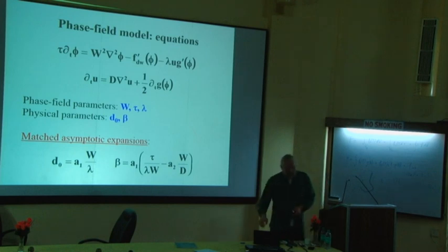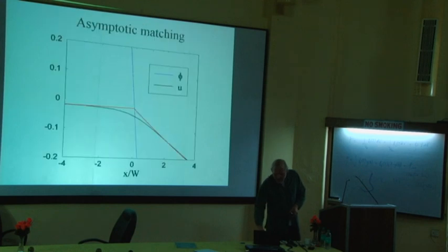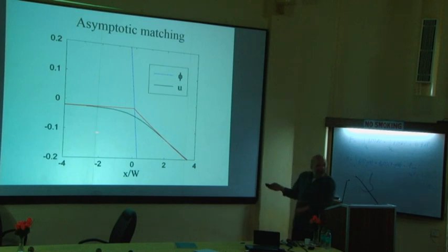Now, what's the second term? The second term is actually quite interesting and quite non-trivial, because you see, in reality, the temperature varies across the interface. Okay? I have told you that the temperature determines the driving force for the phase transition. So you see that actually the driving force is not constant through the interface, it varies through the interface. Okay?